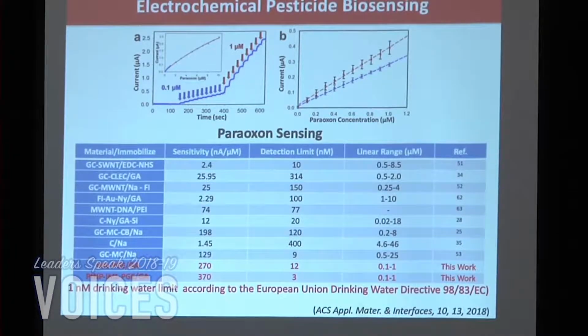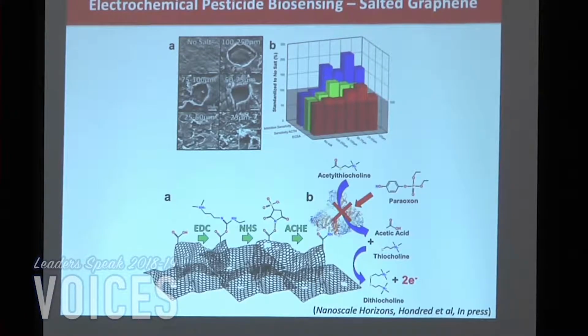In all, you'd expect these pesticides to be high in a farm field, but as they trickle down into the water supply, could you monitor them in the drinking water if they got in there? The EU Directive has a drinking water limit of about 1 nanomolar concentration. In our detection limit, we got pretty close to that. Ours is there at the bottom in red. This is one of our graphene electrodes, and we got a detection limit of about 3 nanomolar. So we wanted to improve that a little bit to get down to the 1 nanomolar detection limit.